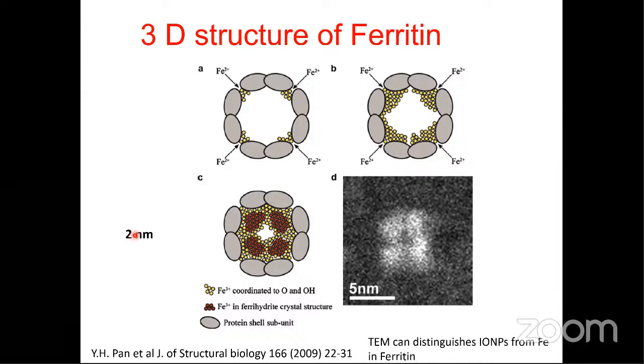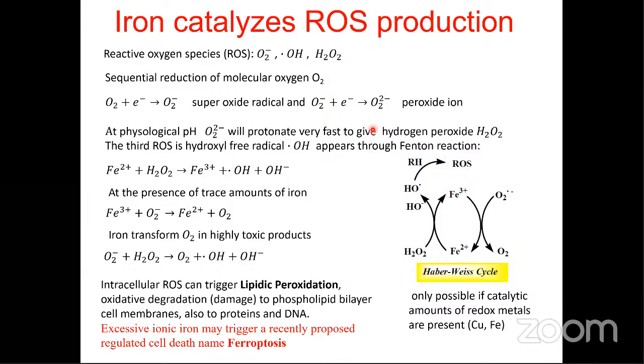What else with iron? Iron catalyzes reactive oxygen species too. A sequential reduction of molecular oxygen can produce the peroxide ion. Once we have peroxide, at physiological pH it will protonate very fast, and then it will be hydrogen peroxide. When we have hydrogen peroxide, it can interact with ferrous iron to produce the hydroxyl free radical. So we have here the hydroxyl free radical, and also in the presence of a trace amount of iron, the peroxide ion can interact.